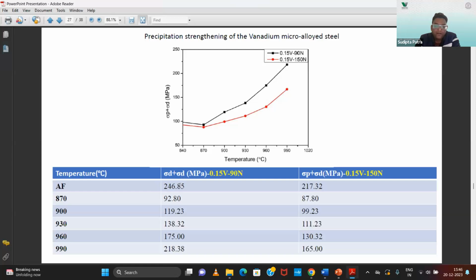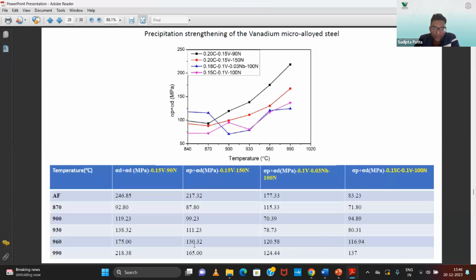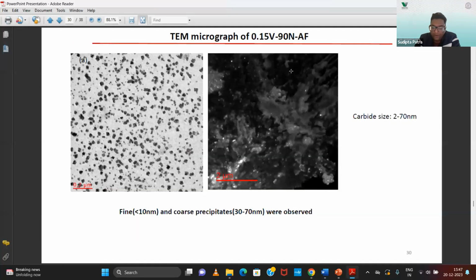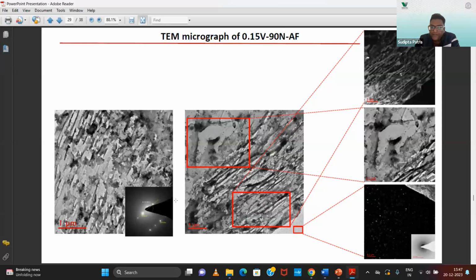With these 4 alloys we could calculate the precipitation strengthening, and we can see that 246 MPa precipitation strengthening itself can be reached with high nitrogen and a little bit lower nitrogen, 90 nitrogen and 150 nitrogen. In the as forged condition we could get these values, and at higher normalizing temperature also we could get very high precipitation strengthening values. So you can observe the high strength and high precipitation strengthening. The TEM observation of the precipitates is presented here.